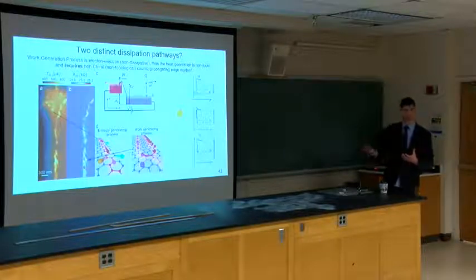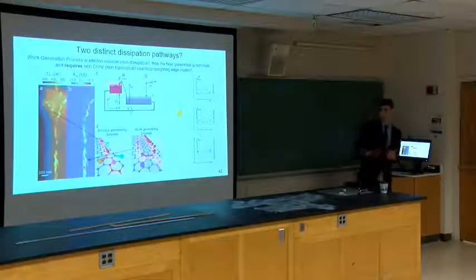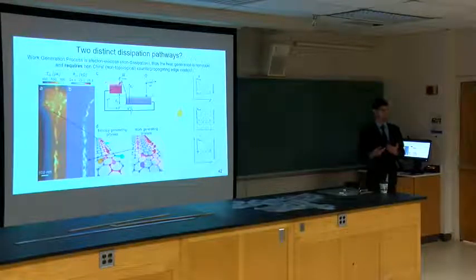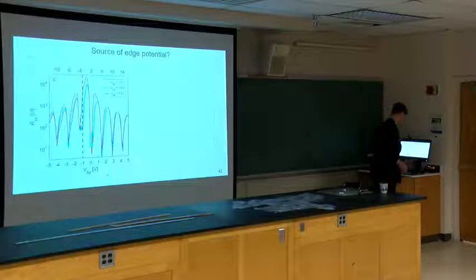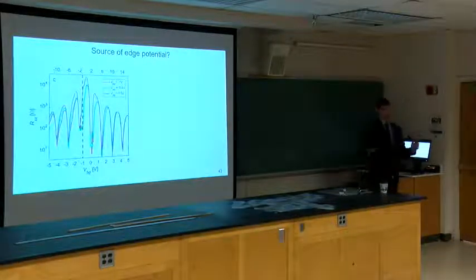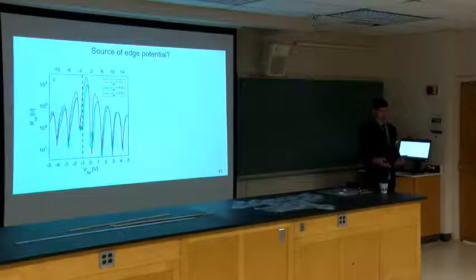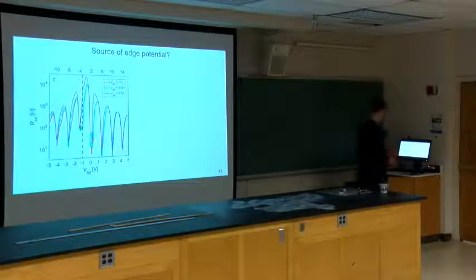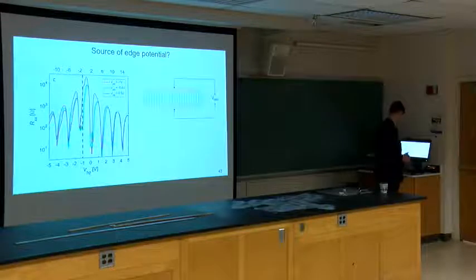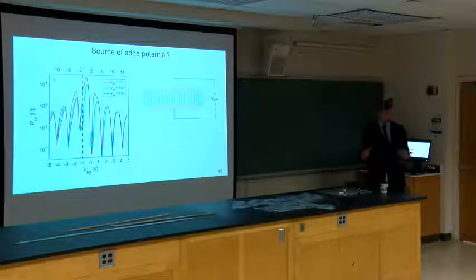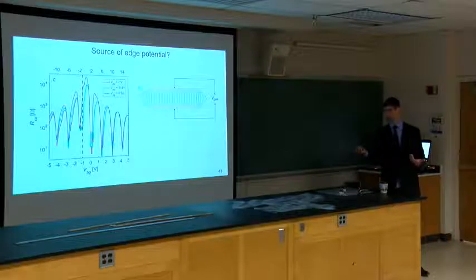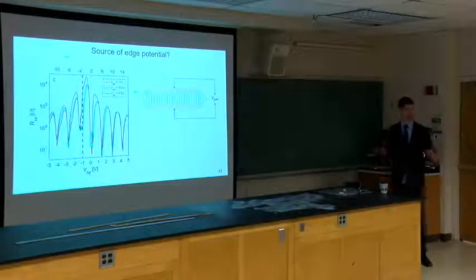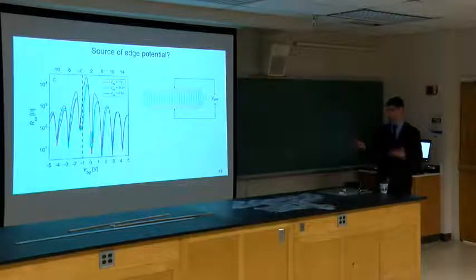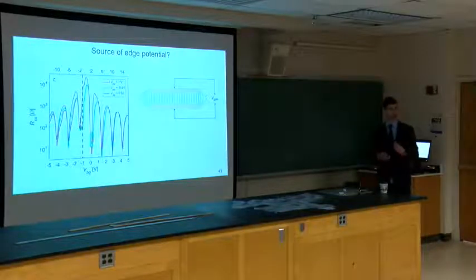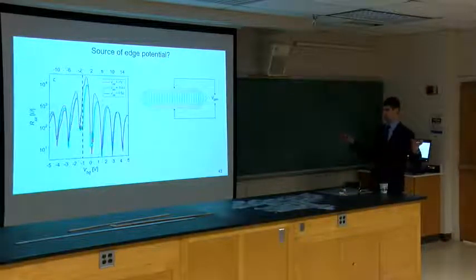We see a little dip, which is some type of edge field or edge doping. And as I said before, this type of perturbation shouldn't affect the quantum Hall effect. We shouldn't get dissipation from this. But we do when it's not just local, if it's actually a global property of the system that we just didn't think was there. Well, for the source of the edge potential, the first easy explanation would be, think of a capacitor. If you're near the edge, you have flux lines that kind of crowd at the edges. You can get a little bit of extra density, and that could explain it, right?